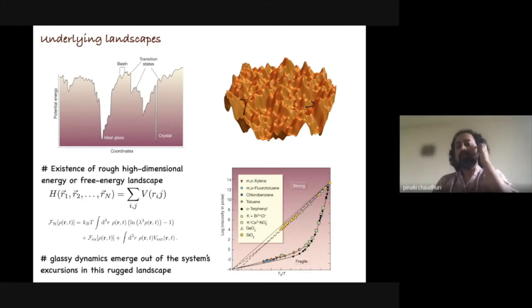As the system evolves, it always tries to minimize the energy, and as it does so, it falls into one of such local minima. Sometimes thermal fluctuations may kick the system out of this local minimum, and then it will hop to the nearest minimum and so on. Because the landscape is so rough, the system evolves through a very slow dynamics. This is essentially the reason why this slowing down of the dynamics happens as we approach the glassy state.